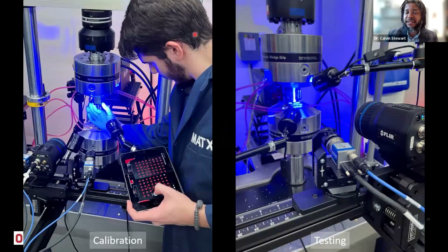Now, there's some challenges in this technology. There's science to it, but there is some degree of art. Whether it's applying the speckle pattern and making a speckle pattern that can survive 2,000 degrees Celsius. Not easy. Whether it's the calibration of the cameras so that we can get the Z dimension to understand what out of plane dimension is, or even to filter the light, to saturate the sample with a certain wavelength, the blue wavelength of light, to filter down to certain wavelengths that we see into our monochromatic cameras so that we can cut the glow of samples, of rocket engine samples, and be able to see their strains.